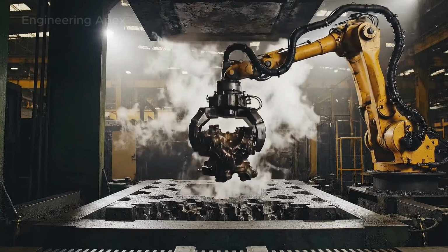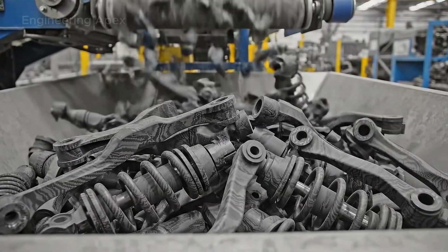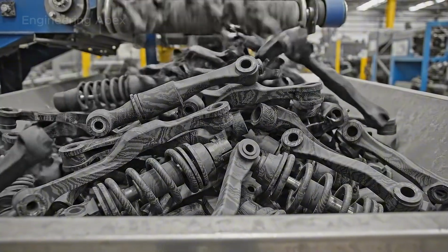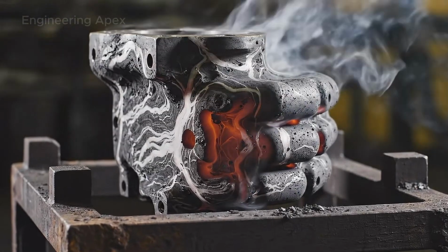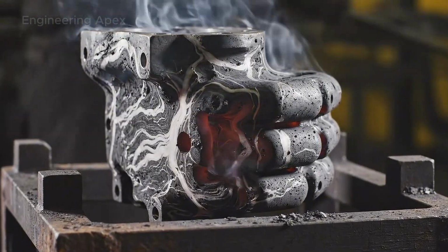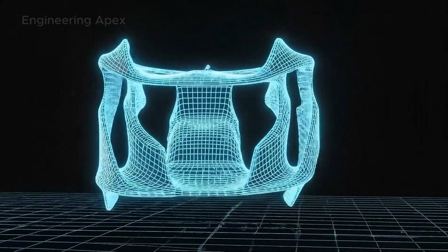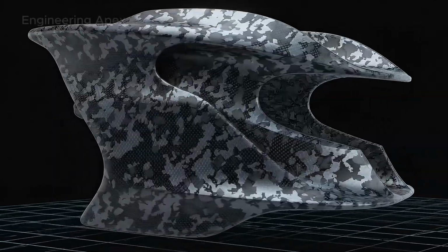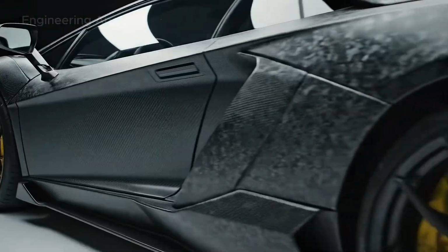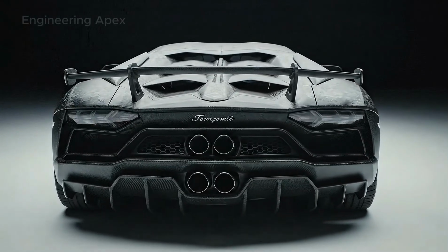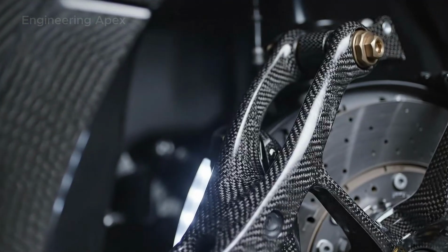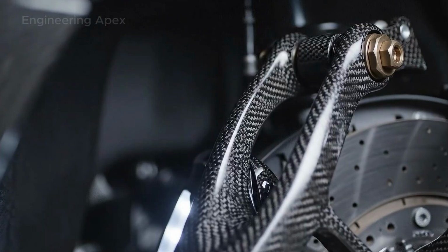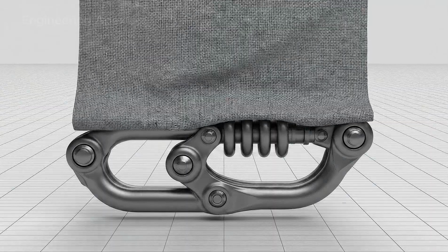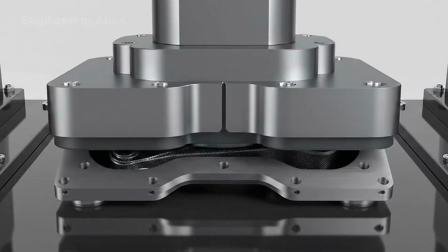For structural composites, the ability to stamp out monocoque components with the speed of stamped steel, yet retaining the lightness of carbon. This ability to make the material flow did more than just speed up the clock. It liberated the design engineers from the geometric tyranny of the 2D weave. When we examine the Sesto Elemento, the manifesto car for this technology, we see suspension control arms made not of cast aluminum, but of forged composite. Producing such a complex three-dimensional shape with woven cloth would require intricate cutting, darting, and overlapping, introducing potential failure points at every seam. With the compression molding process, the material simply fills the void, allowing for variable thickness and integrated mounting points.